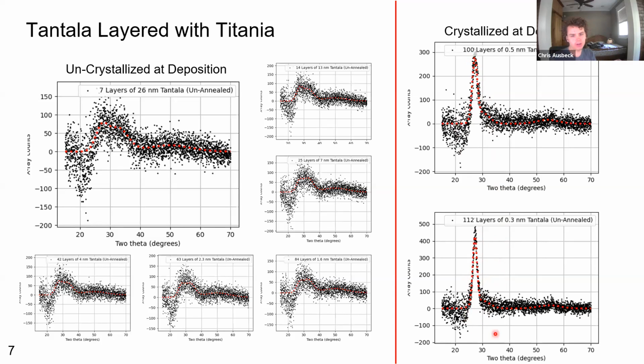And we believe what's going on here is that these are very, very thin layers. So once you reach 0.5 nanometers and 0.3 nanometers, what's likely going on is that there is such a high mobility of these molecules that they can move around so easily with these very thin layers that they end up mixing together and forming mixed crystal lattices that can crystallize at a very low temperature, at a very low melting point.